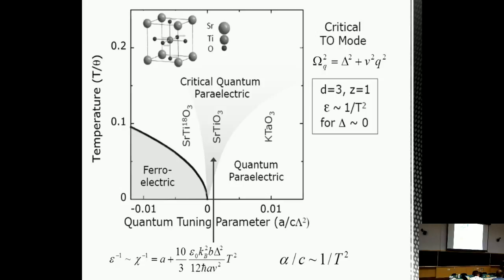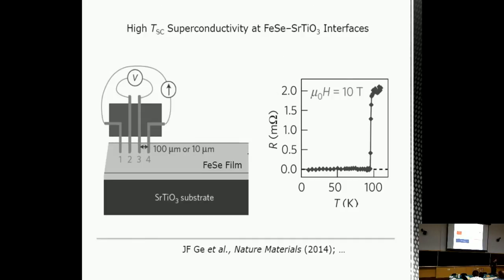I have perhaps a different question. We saw strontium titanate earlier this morning underneath iron selenide. Do you think the mechanisms you have here in bulk strontium titanate may play a role at that interface? I think it hasn't been checked out in detail, but yes, it's certainly a possibility. And that's one of my extra slides: look, you go from 1 Kelvin up to 100 Kelvin. What's the reason for this? Maybe it's possible that you could here be combining the polar phonon, the hybrid polar mode mechanism, with the magnetic pairing mechanism. So maybe you have 2 bosons helping to support superconductivity in this case.